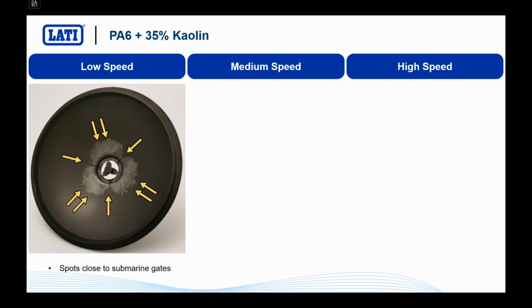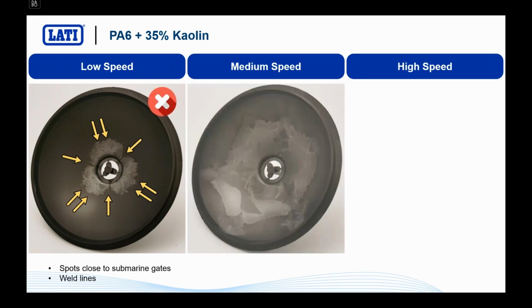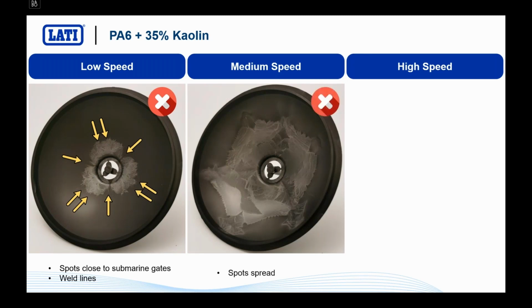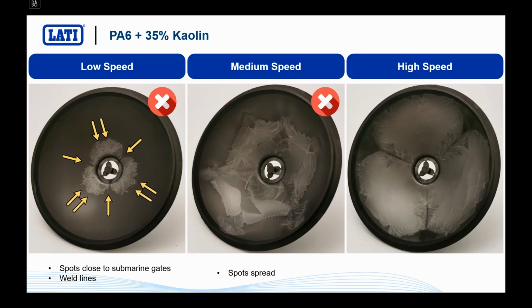This slide is just to focus your attention on the fact that by using a 3-gate injection location, you still have the same problem. I mean, it is even worse because you do not have only very bad looking spots and a dull, very opaque surface, but you also have terrible weld lines. Terrible weld lines. You can see how evident they are here. Even at high speed, you have the most terrible, I would say, weld lines and a totally unacceptable surface finish.